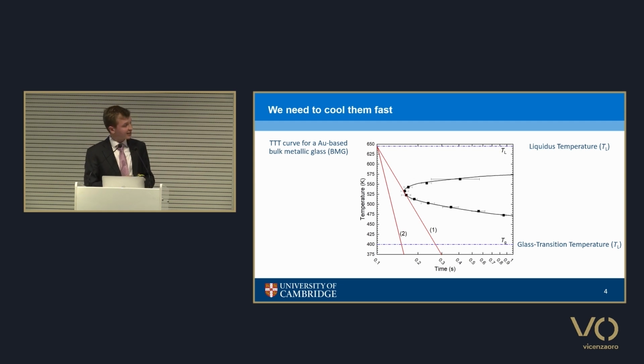So you'll see two red lines here. On the first one, labeled 2, we have a critical cooling rate that will entirely form a glass. The second line, labeled 1, is for a critical cooling rate to avoid crystallization. And that intersects this black C curve here, which is the measure of the time for crystallization to occur as a function of temperature. And if we cool fast enough, we will reach this glass transition temperature. And that's the temperature at which the atoms are effectively frozen into the glass and they are thermally arrested.